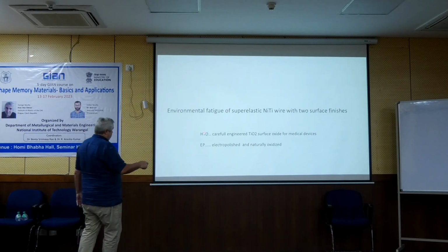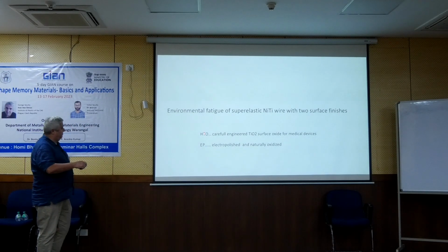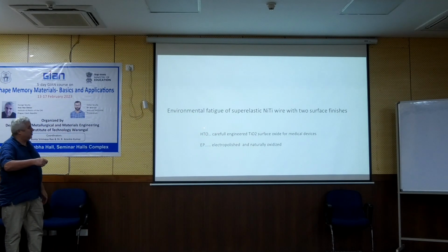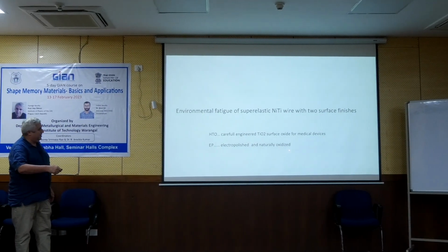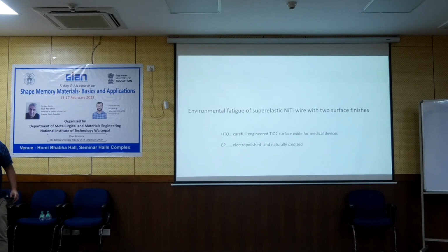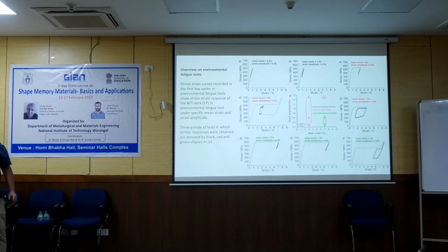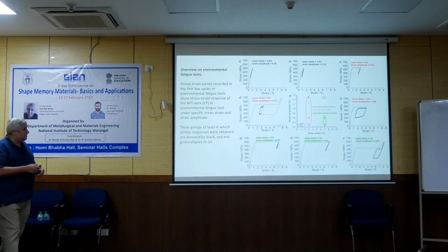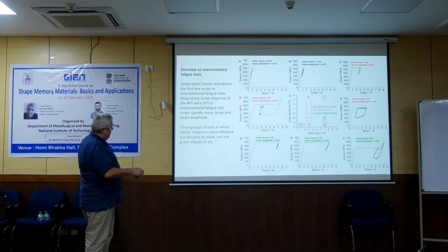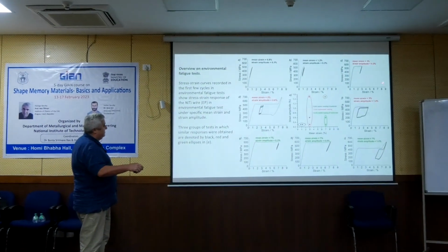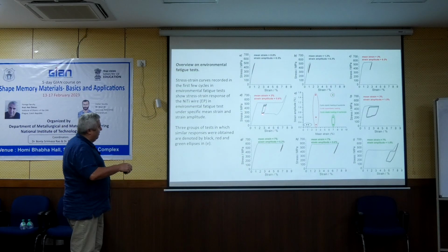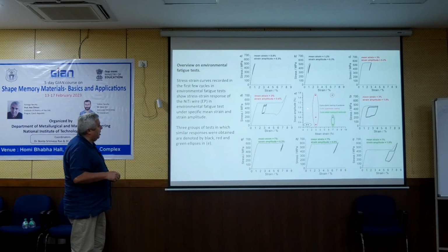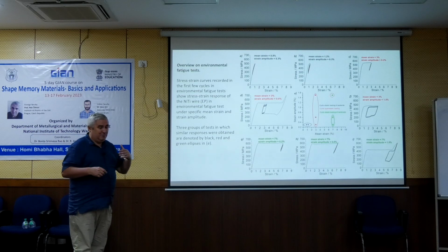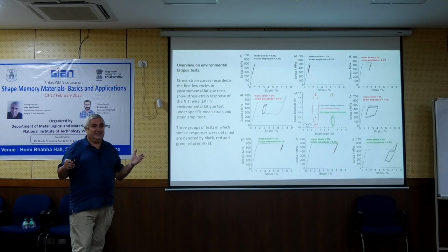This is the result of long research on how to optimize heat treatment of the surface oxide and how to do the electropolishing. We spent lots of time testing and analyzing these wires, and basically the conclusion was about the same: if we test in the elastic range, we get very long life. If we test in the martensite range, we get long life. The problems are in the middle, and this is the case for both wires. But the HTO wire showed much poorer results than the electropolished wire.